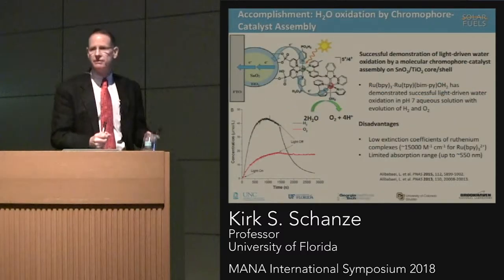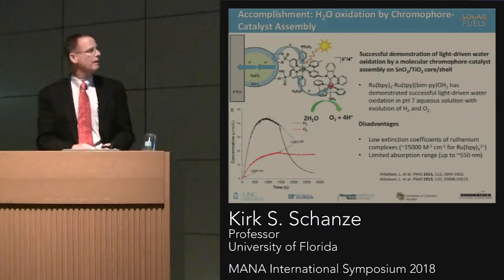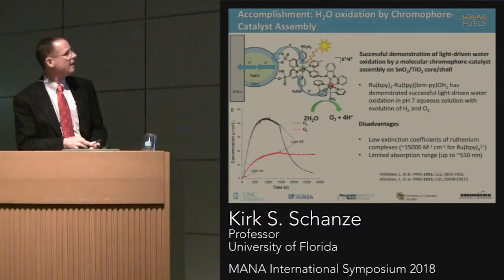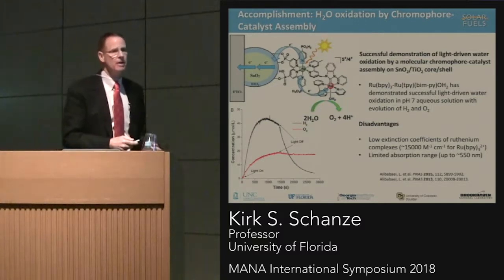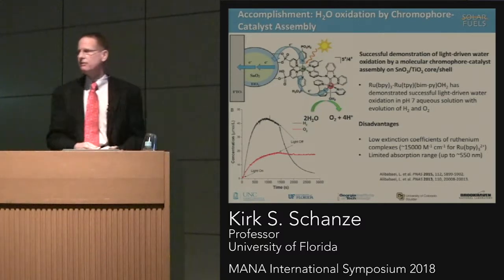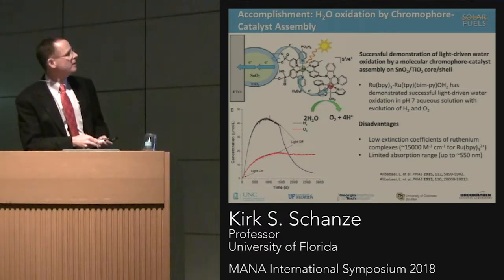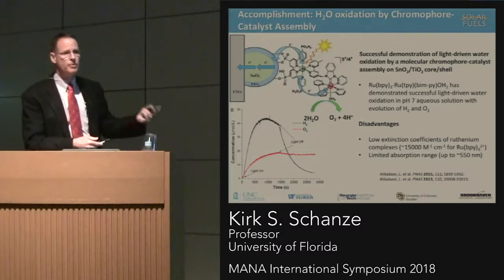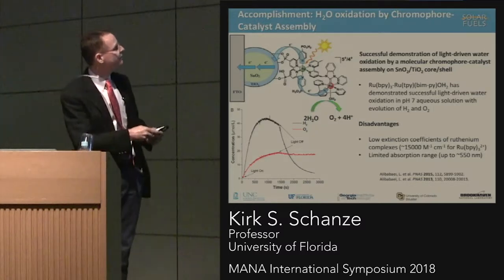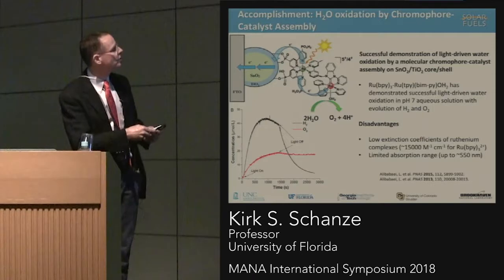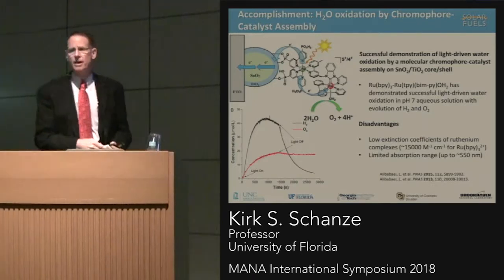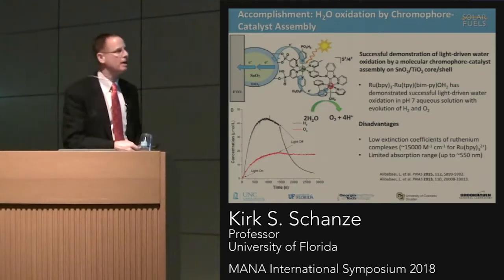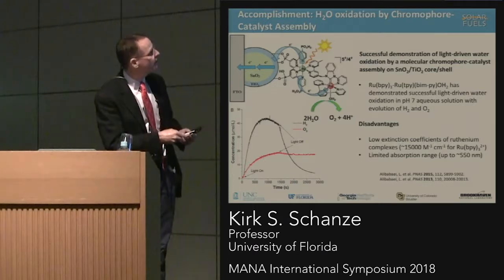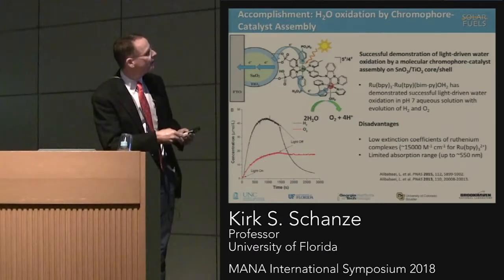Now, just to give you an example of some of the work that has come out of the center that's been a highlight is the system that I show here. This is a dimeric ruthenium complex that illustrates the features that I've talked about. Namely, there's a ruthenium polypyridine complex, much like ruthenium tris bipyridine. It's functionalized with phosphonate groups which allow it to anchor onto the surface of a metal oxide such as titanium dioxide or tin oxide.